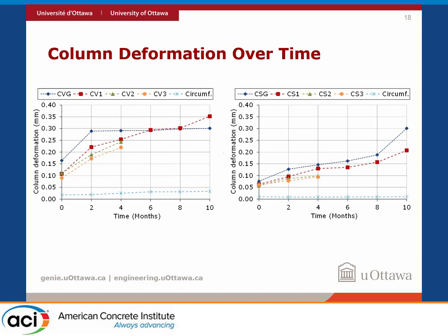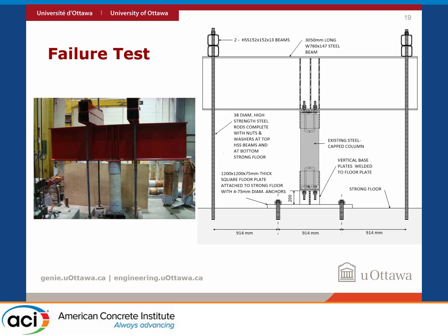Once we subjected the specimens to corrosion, we tested them to failure. So this is the setup that we used for testing them. The columns were loaded by this beam up here that was connected to the strong floor of the structures lab through four 38 millimeter steel rods. We apply tension on one side of the column, subjecting the column to compression, and the rods on the other side were used to stabilize the system. And by tightening the nuts of the rods on one side or the other, we could control the amount of eccentricity and bending moment applied to the column.